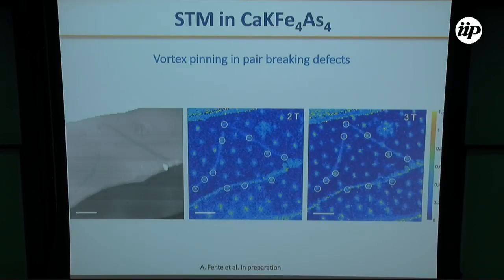Then we have studied the effect of these pair breaking effects in the vortex lattice, and to do that we again chose a region with a large amount of defects, these steps, and looked at what happened with the vortex lattice at two different fields, 2 Tesla and 3 Tesla. So we can see that these defects produce an enhancement of the density of states, so they produce pair breaking as we observe in zero field.